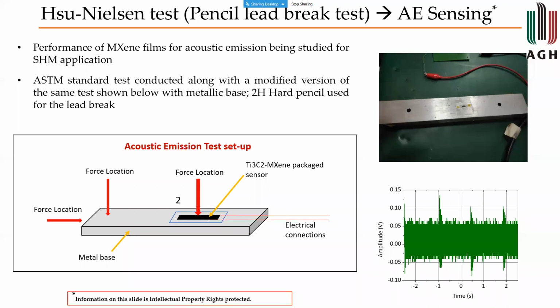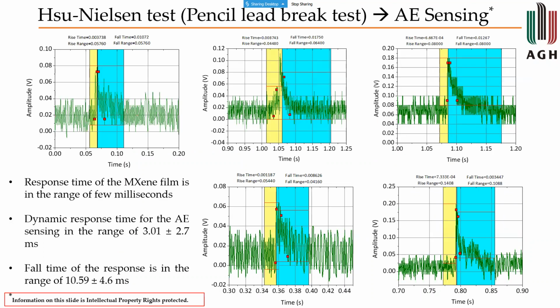So the result that you see on the right bottom corner is basically a hammer hitting the metal piece multiple times, which gets captured. While this is one crude experiment that we performed, with the pencil lead break test, we did have some results coming out without any signal processing. In the initial phase, we didn't want to have a lot of signal processing, to see if the gain that we have or the kind of response that we have is quite considerable, and what kind of amplifiers could be used.